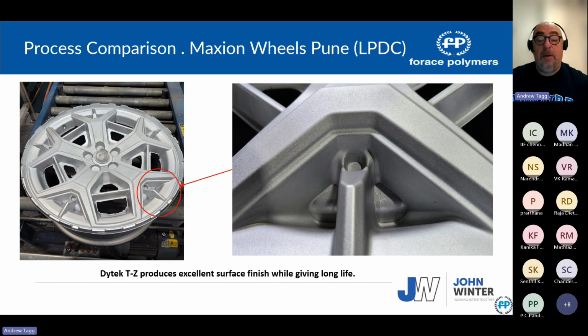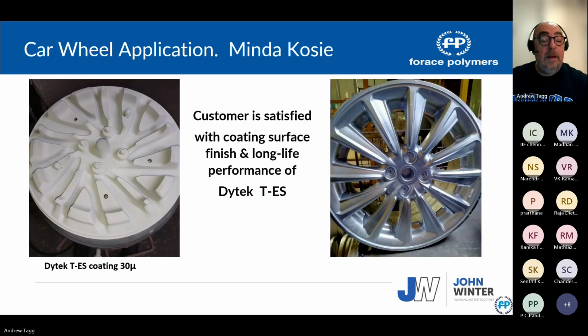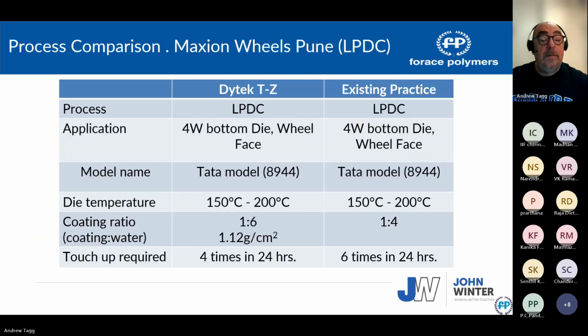And the important bit was, if I could go back one, with our coating, you will see the big thing was the touch-up time. Basically, in the original process, they were touched up 6 times in 24 hours. With ours, they were touched up 4 times in 24 hours. So again, you see the coating is longer life. The coating requires less touch-up, and therefore more production.